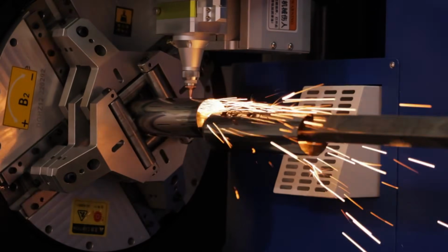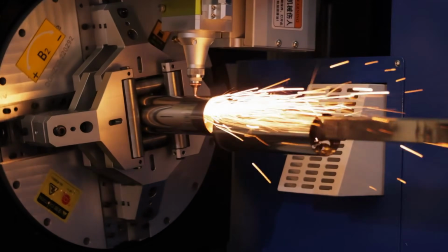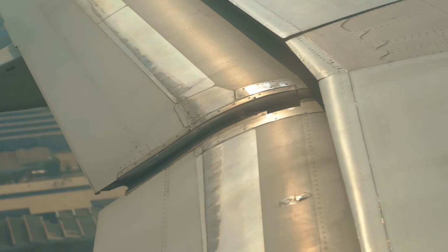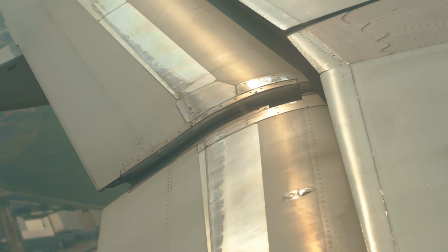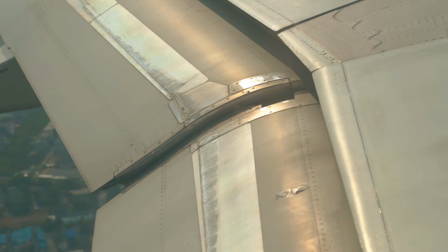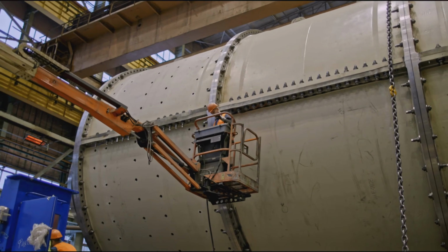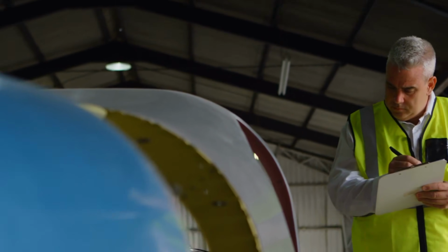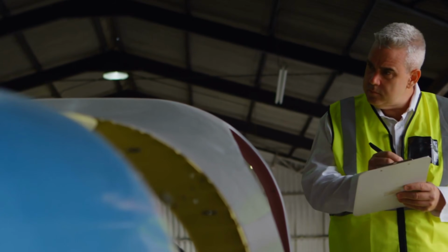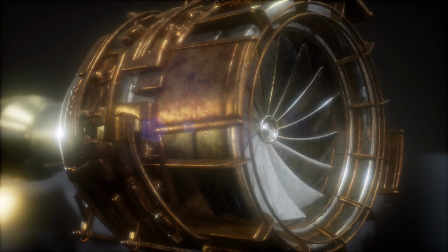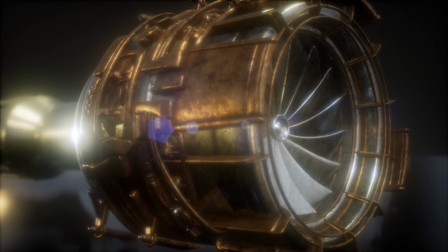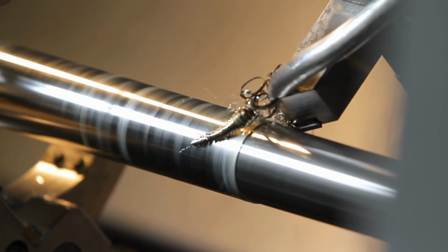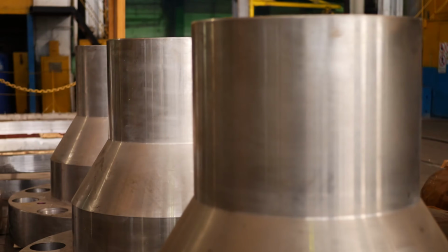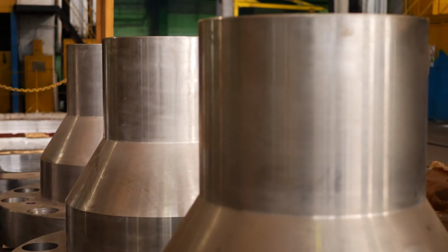The precision required for aerospace titanium components defies imagination. Turbine blades must maintain airfoil shapes accurate to within 0.005 of an inch across their entire surface, because even microscopic deviations would disrupt airflow and reduce engine efficiency. Surface roughness specifications require finishes smoother than a mirror, achieved through multiple grinding and polishing operations using diamond abrasives finer than face powder.